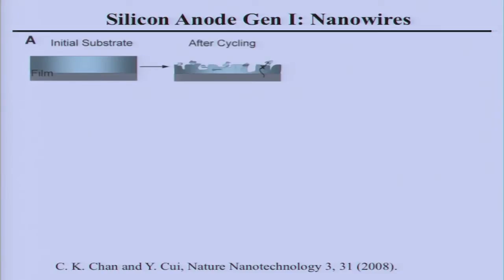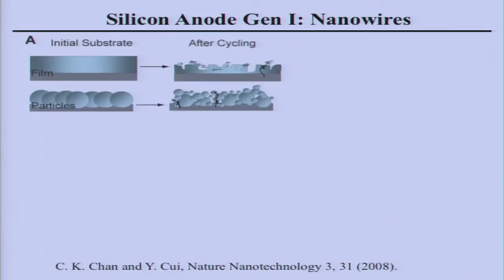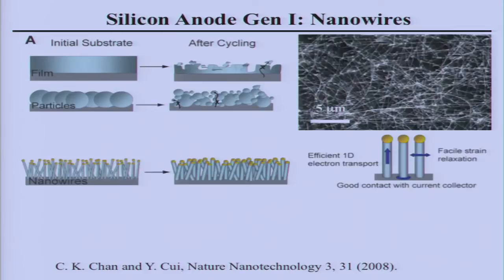But recognize the film will break and the big particle will break. And with the nanowire at that time, the hypothesis is that the diameter is so small that when the volume expands once lithium is inserted into the crystal structure, it will not break. You can ship the electrons going into the nanowires, with lithium coming from the surface. So at least we can solve the breaking problem. This is the first significant progress along this direction.